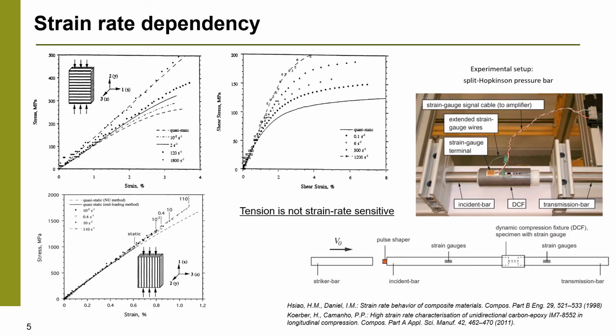A tubular specimen may be considered a structural element. So on the lower level of coupons, a very popular impact experiment is based on the split Hopkinson pressure bar. It records reflected and transmitted strain waves, so strain in the piece of specimen can be determined. As you can see in the example of test results, transverse and shear loading diagrams are highly nonlinear and rate dependent. They have significant hardening with rate growth. In fiber direction, the hardening effect is not so meaningful, but ultimate strength growth with impact rate exists. Also, from literature sources, we can conclude that tension properties are not so sensitive to strain rates, so they can be omitted in the analysis.